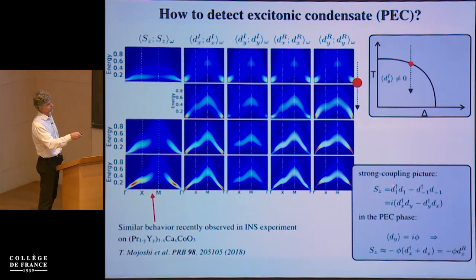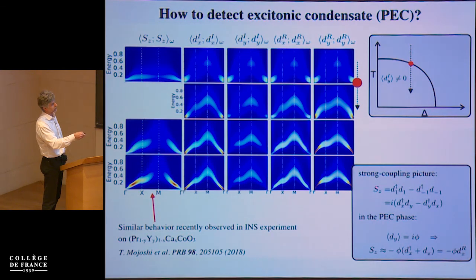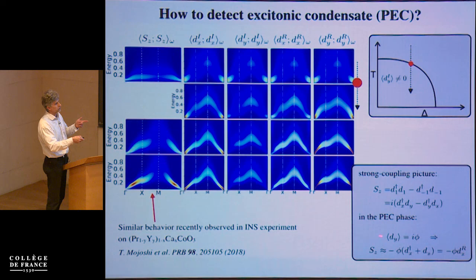If we go back to the relationship between the spin moment and the excitonic operators here, we realize that when we go to the condensed phase, we can replace one of these operators by a constant. So in our case, the direction of the order parameter is such that this dy is proportional to i times a real number.